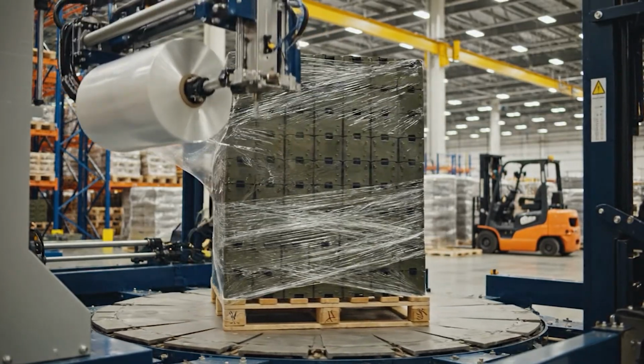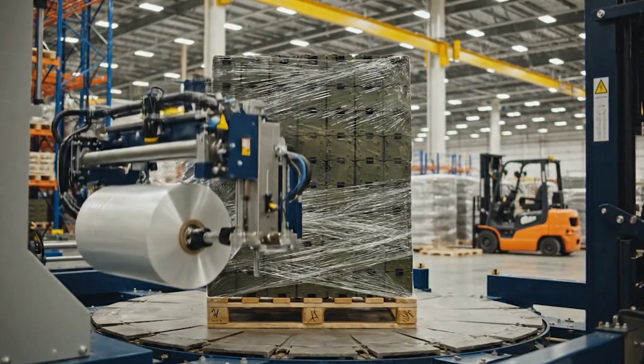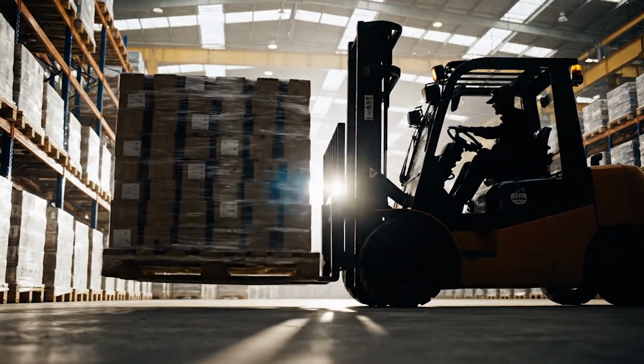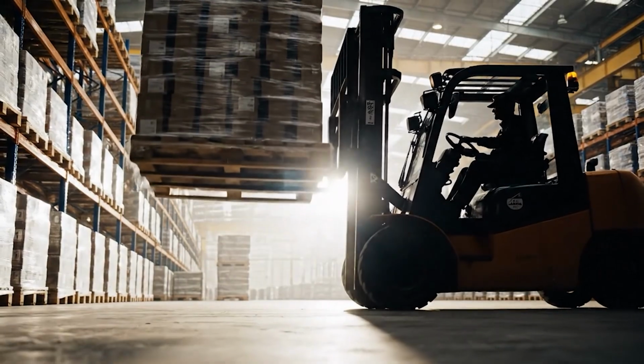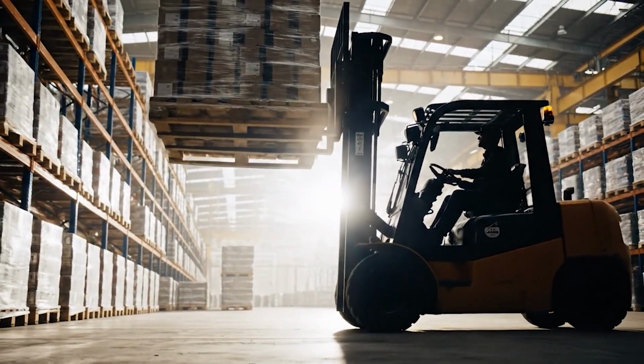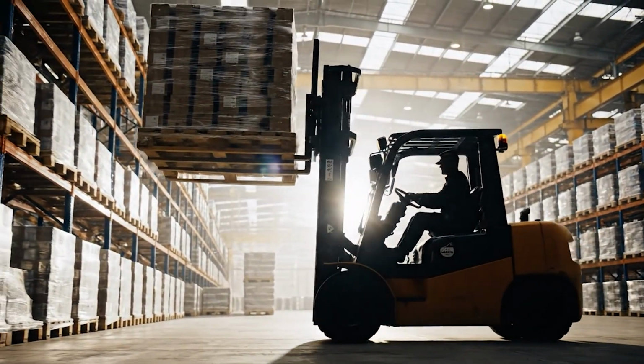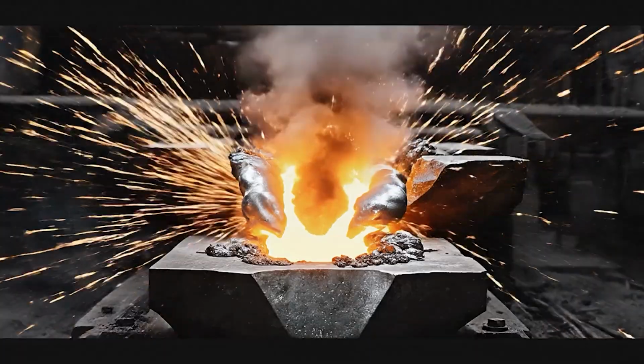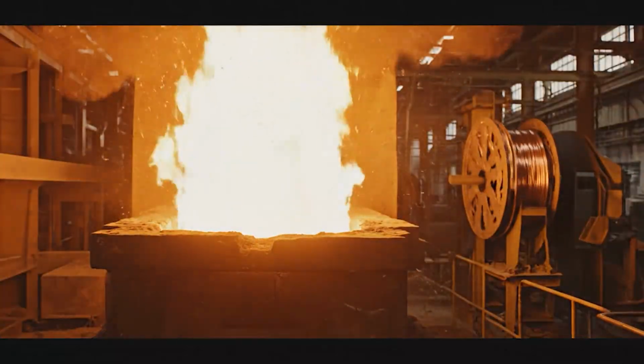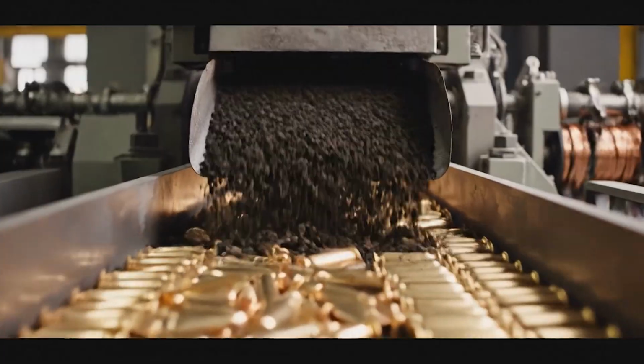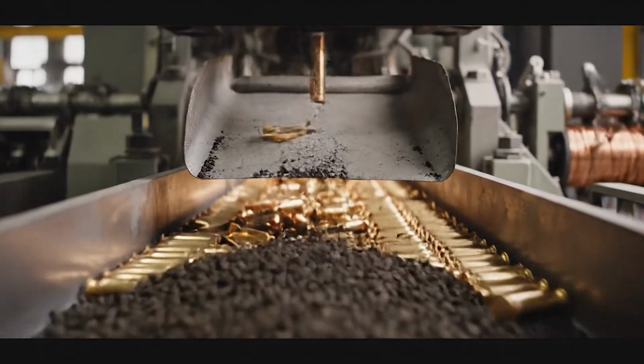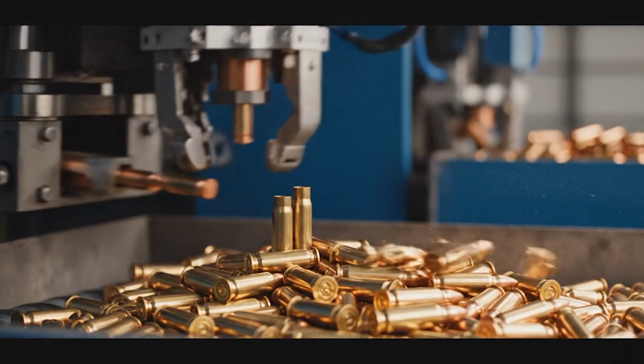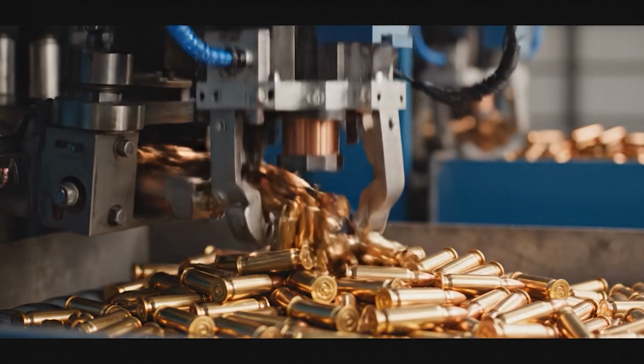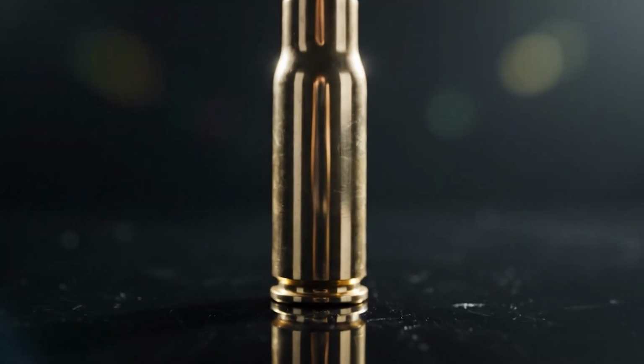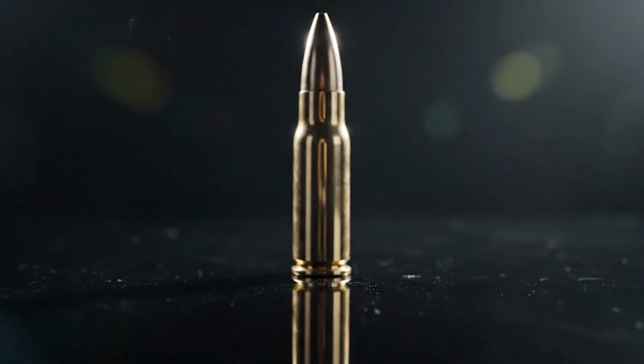If the velocity is too low, the batch is rejected. If it's too high, it's dangerous. Simultaneously, a piezoelectric transducer measures the chamber pressure. The graph on the computer screen spikes to 55,000 or 60,000 psi in microseconds. The pressure curve must be smooth and consistent. They also test for accuracy. At the end of the 100-yard tunnel, the bullets hit a target. The group size, the spread of the bullet holes, is measured. For match-grade ammunition, the spread must be smaller than a dime.